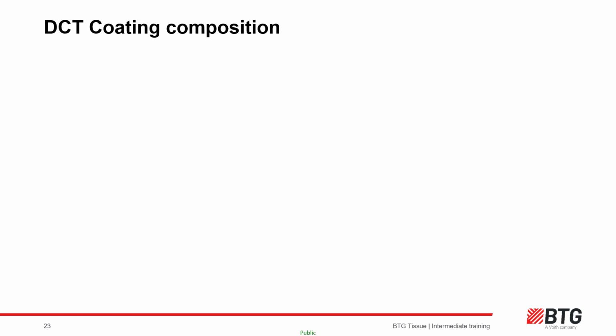Now we have established there's more to Yankee coating layers and composition than meets the eye, so we can begin to understand some of the complexities. We control Yankee applied chemistry to a specific amount of milligrams per square metre by product grade, usually fixing base and altering release to control sheet adhesion and sheet control off the blade to meet end product specification, to help rebuild and to avoid slack edges which can lead to breaks.